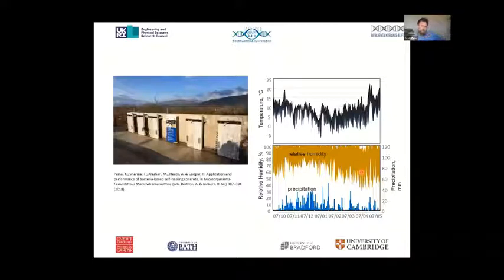Abir has already referenced the RM4L site trial, and as part of this site trial, we demonstrated a bacteria-based self-healing concrete in real environmental conditions. And we've got to be honest, it was slightly less successful than we hoped. But we always suspected that the main contributory factor to that was temperature. And indeed, the average temperature was around 7.5 degrees centigrade throughout the site trial, whereas the bacteria that we use have never been known to be active below 15 degrees centigrade.